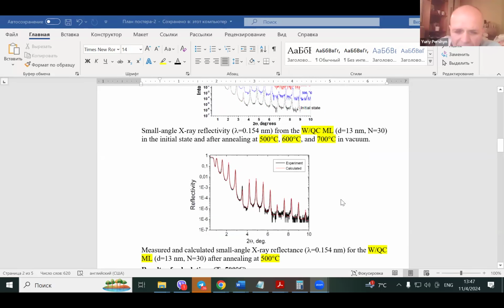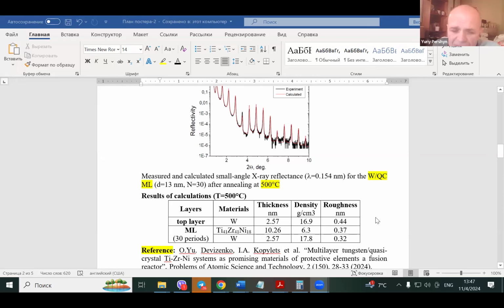This small angle diffraction curve is for multilayer annealed at 500 degrees centigrade. So we can see that it has quite good layering, and the red line represents the fitting curve, which allowed us to get some characteristics of layering materials represented in the tables. And that is thickness of multilayer, their density and interface roughness.